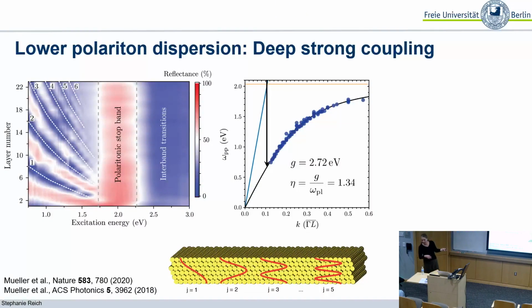The extent of the energy gap was not as large as we expected from theory, and the reason is that at roughly 2.3 eV, you have interband transitions in gold, so the description as a plasmonic material no longer applies to these energies, and everything breaks down and you get very strong absorption. And underneath this polaritonic band gap, there are these fan-like dependencies of the lines on the layer thickness, and they correspond to these standing waves inside our crystal. You can use them to construct a dispersion where you plot the energy of the excitation versus the inverse wavelength, which corresponds to the wave vector across the growth direction we are looking at.